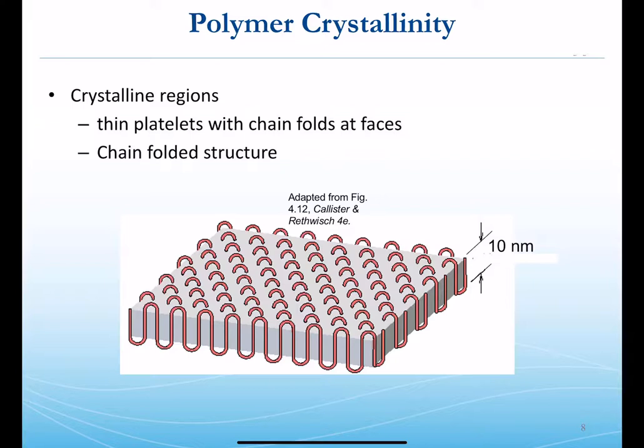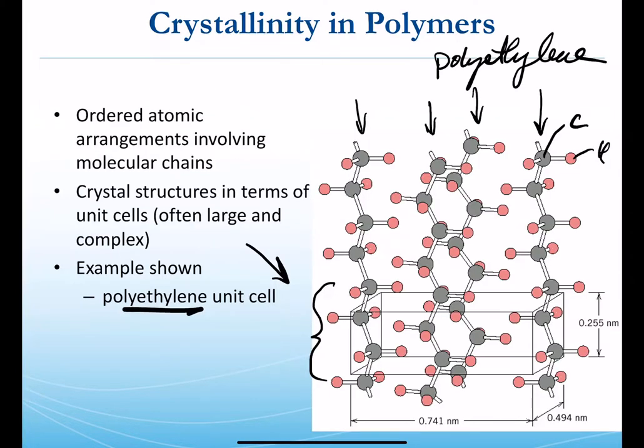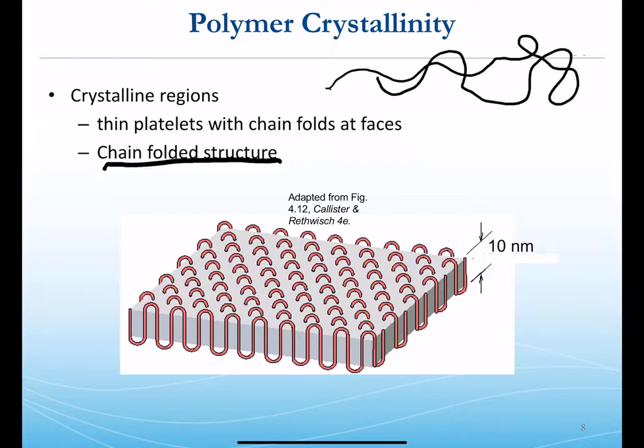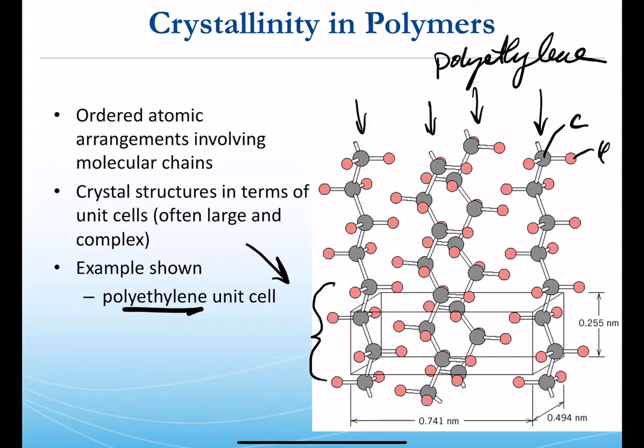So what does that model look like? There's a unit cell, and chains are often quite parallel to one another as they pack. Extending that model further toward the bulk object — what do crystalline regions look like? The model is a chain-folded structure. One polymer chain, the long primary-bonded noodle we've been describing, if carefully cooled from the right temperature, will fold on itself and pack next to its neighboring chains per the conditions of the unit cell — per the spacing and arrangement of atoms.